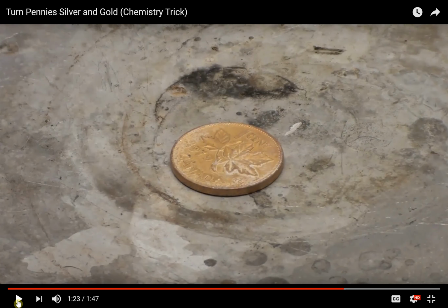Why? Because there's a concentration gradient. There's less zinc in the copper layer of the penny. So zinc wants to travel in. It's moving down the concentration gradient. And as it does so, it turns into brass, right? Brass is a different color. So it's not turning it gold. It's not turning actually into gold atoms. It's just turning gold color because it's turning into brass.